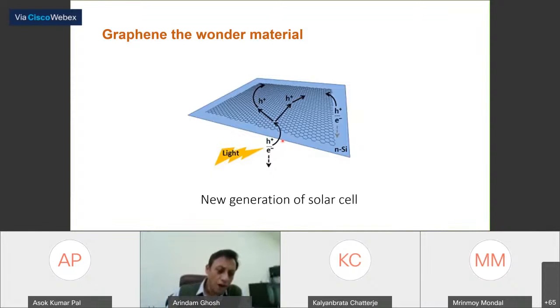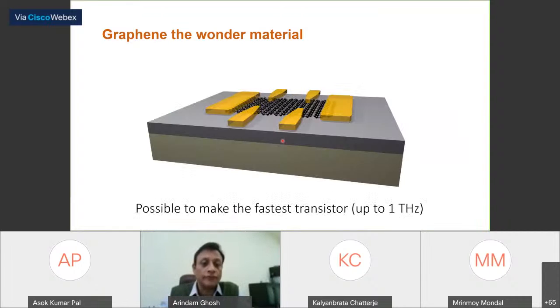What we will be discussing primarily today is graphene as a field effect transistor, and you can actually use these to make extremely fast transistors. One of the big problems of silicon-based transistors is that the mobility of electrons or holes in a silicon transistor is just about 200 or so. At room temperature, graphene mobility can be thousands of times larger than that. As a result, you can make much faster field effect transistors, up to a terahertz, which is simply not possible using silicon-based technology.